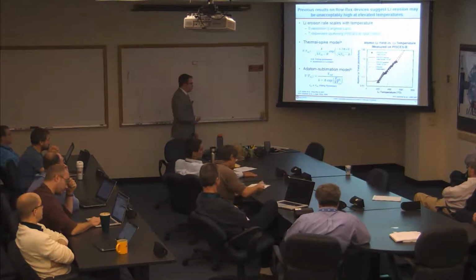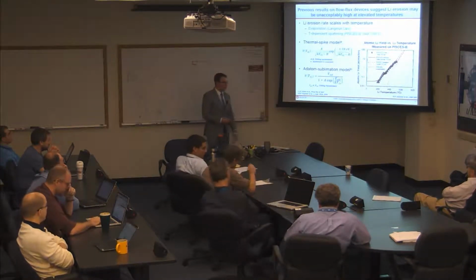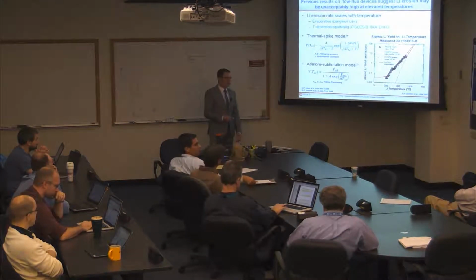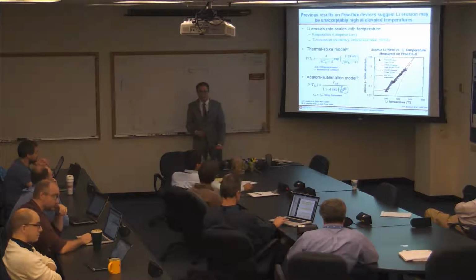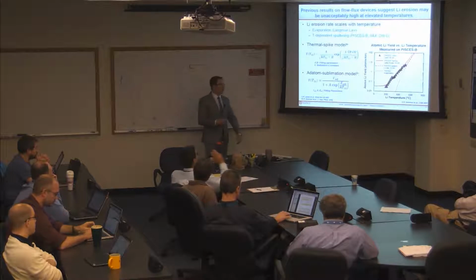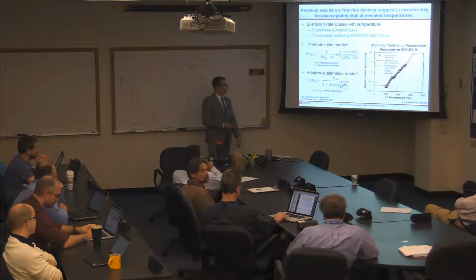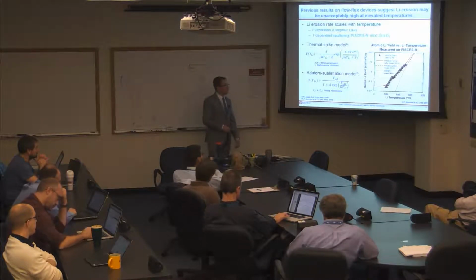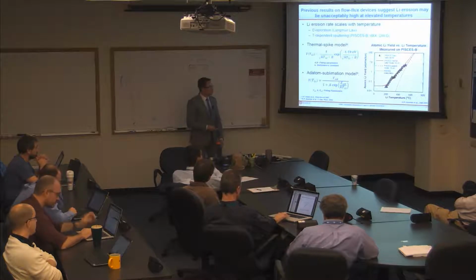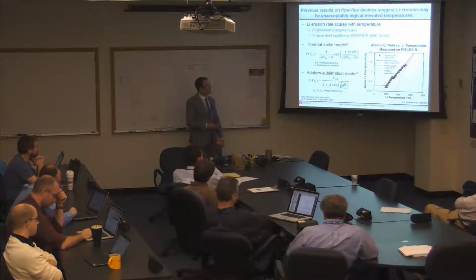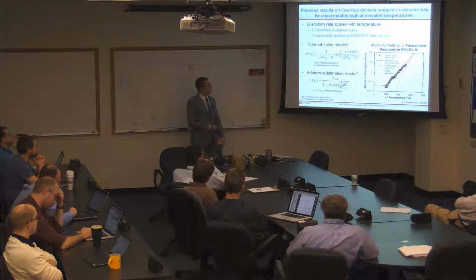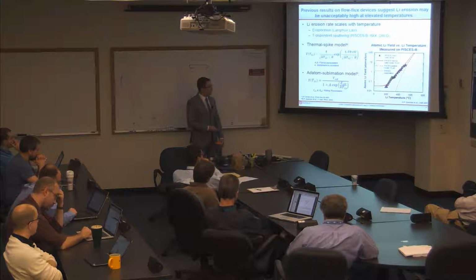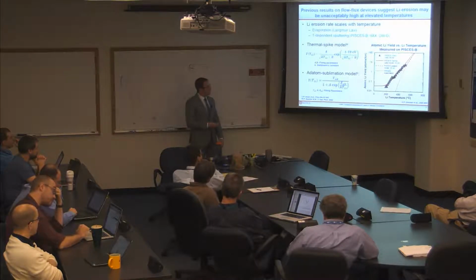However, just to give you sort of a motivation for the existing issues associated with lithium erosion, there have been studies done of the temperature-dependent erosion of lithium under lower flux plasma bombardment. The PISCES-B experiment has fluxes in the 10^21 per meter squared per second range. And the evaporation and the temperature-dependent sputtering, which I'll explain a bit more later, was observed to increase very strongly as a function of temperature.